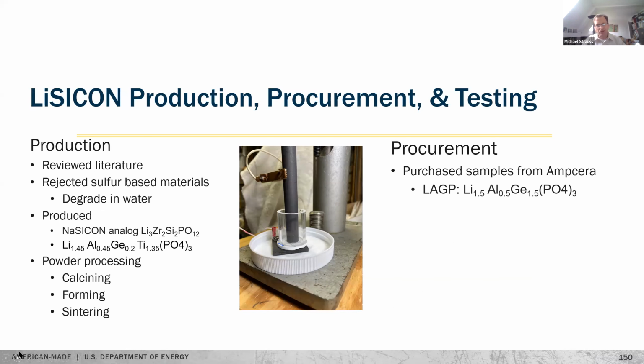We reviewed the literature and we rejected sulfur-based materials because they don't do well in water, even though they have very high conductivities. We made some compositions and we also bought some from commercial processors. The processing is standard ceramic processing. We're talking about grinding, milling, calcining, forming, sintering. It's basically the same processing you would do to make a toilet bowl. This is our test rig. The black rod on top and the black plate on bottom are electrodes.